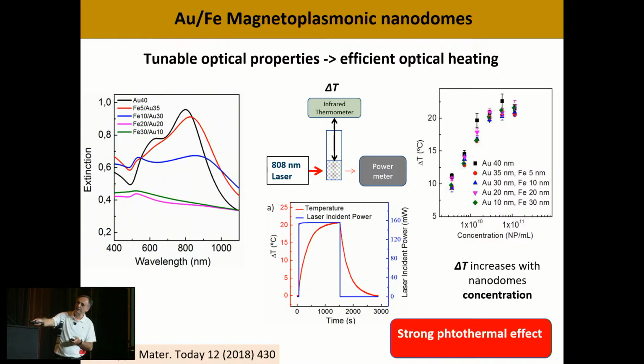You see, we put the laser on, and the temperature starts increasing, and then we switch off the laser, and the temperature goes down. And we see that in a few hundred seconds, the liquid can increase 20 degrees very easily. And the heating depends on the concentration of the nanoparticles, but not so much on their actual structure. You see that the heating is similar for the pure gold or the gold iron nanoparticles. So we have a very strong photothermal effect.